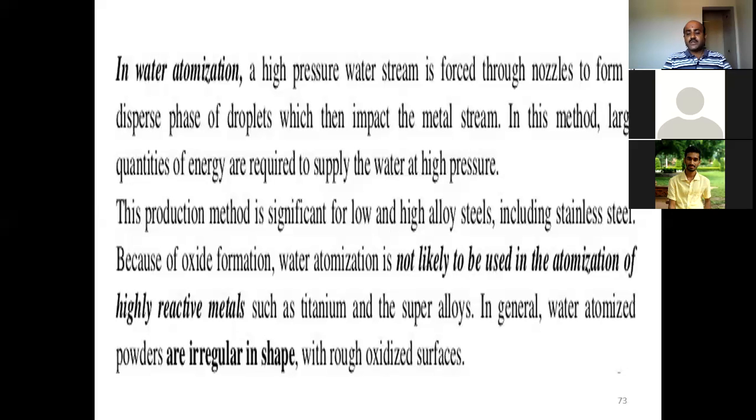Because of oxide formation, water atomization is not likely to be used in the atomization of highly reactive metals such as titanium and superalloys. In general, water atomized powders are irregular in shape with rough oxidized surfaces.